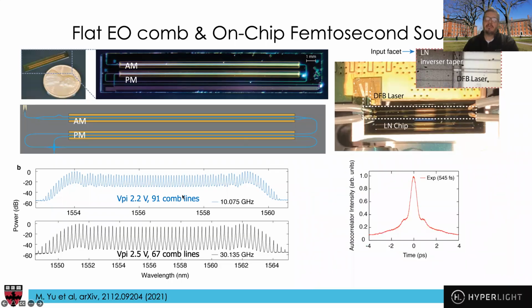When you take this comb spectrum and look at the time domain using an autocorrelator, we get very nice pulses of 500 femtoseconds. So basically we start with a CW laser, apply RF, and generate 500 femtosecond pulses. What I didn't tell you is that it's a little bit of a cheat, because at the output of this lithium niobate waveguide, we have about 100 meters of fiber that is used to compress the pulse.